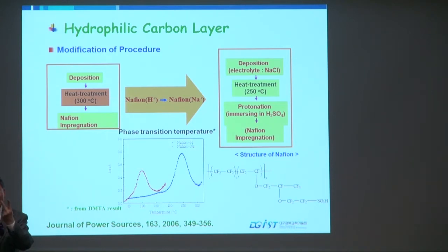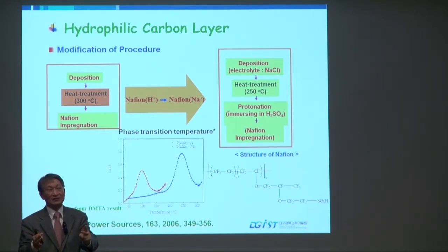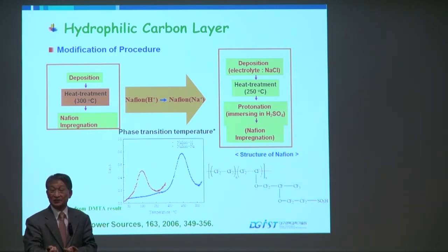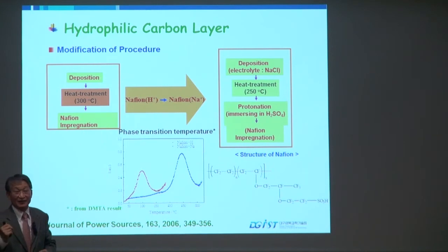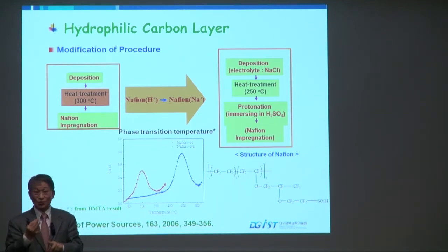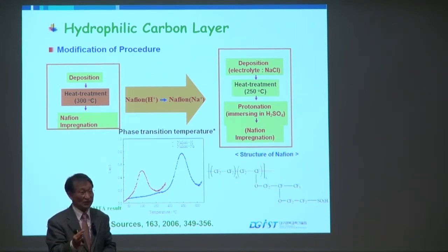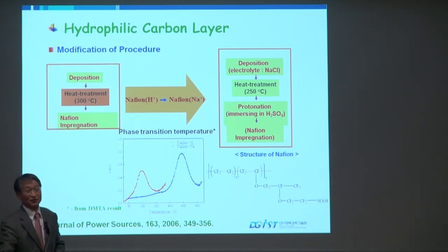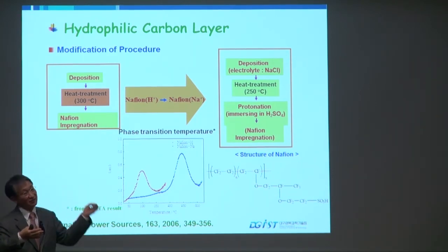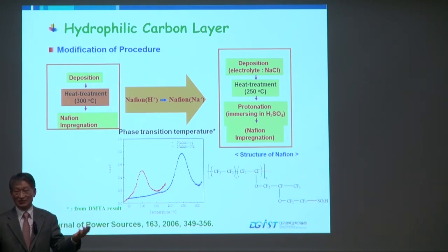The second part is the Nafion high temperature problem. We solve this by transforming the protonic form of Nafion to sodium form. That can be done because electrochemical deposition of platinum occurred in a solution containing sodium chloride, sodium perchlorate. Then this Nafion is very easily exchanged with sodium forms, and the sodium form of Nafion can stand about 300 degrees. So after you do this, the sodium form of Nafion is of course not protonic conductive at all. So after you heat it, what you do is you put it in a sulfuric acid solution for a couple of minutes. Then all this sodium is leached away, then you return back to protonic form of Nafion. Then we are ready in business.